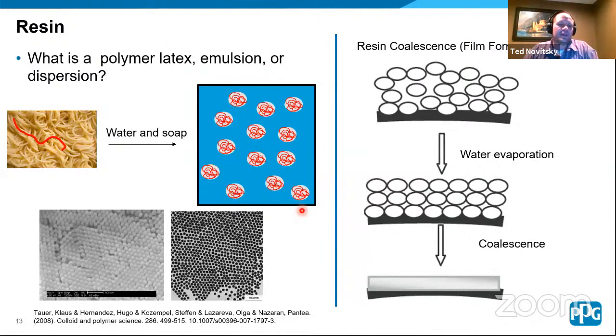And here's a picture of these materials through a TEM here and SEM here that shows that we're not too far from, I mean, while this is just a picture that I drew in PowerPoint, this is actually what they look like, right? And so we need this resin to be dispersed in water. And then after the water is gone, we need it to form a nice film. And so this is what we call coalescence in the paint and coatings world. So we have these polymers that are dispersed in water, and as the water evaporates, they start to concentrate, and the particles start to touch each other.